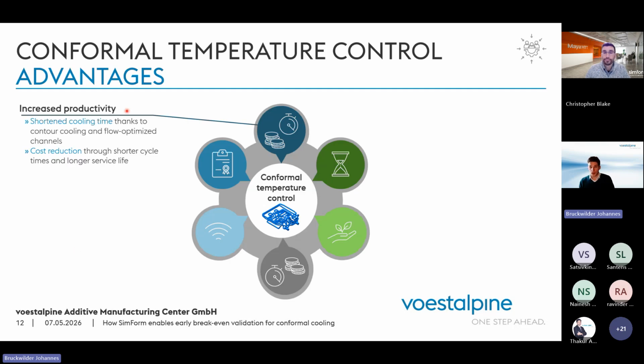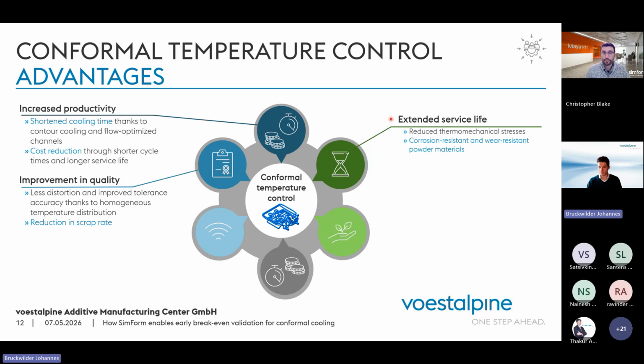And that's the biggest advantage that we achieved in the last years, to really shorten the cooling time, because we have a close contour conformal cooling. And of course, in the end, a shorter cooling time ends up in a shorter cycle time. And this ends up in a cost reduction. Another important factor is that because we are using powder materials that are corrosion resistant and wear resistant, we really have an extended lifetime. So we can go for millions of shots, and that's proven in various applications. With a conformal cooled insert, you don't need to worry about lifetime. It's really, really great what you can achieve there.